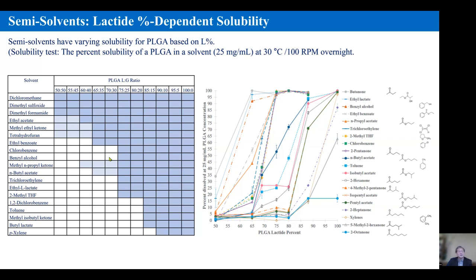The same thing goes for other ratios too, like ethyl benzoate: 60-40 dissolves, does not dissolve, but 65-35 dissolves. So what this shows is that PLGA, even though the LG ratio is seemingly a little bit different, becomes a totally different polymer, partly because of the blockiness we talked about in the first talk, partly due to the blockiness differences and many other reasons. They are different polymers.